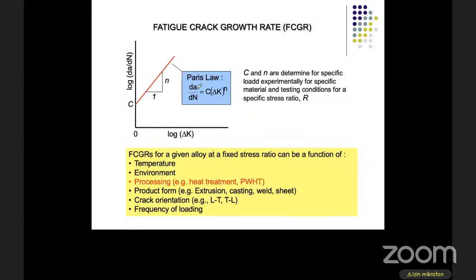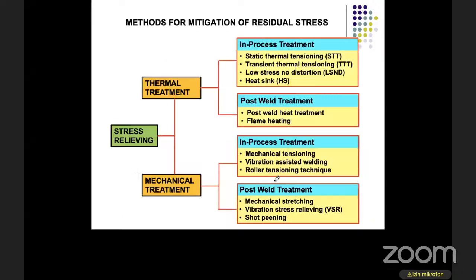And then we focus on the Paris region. From here we will get the fatigue crack growth rate, which is da/dN, and then we can get the Paris constants, which are C and N here. And then these C and N values can be influenced by many factors, like temperature or environment, and then processing, post-weld heat treatment, and so on. So this is my research. We have done some of this work.